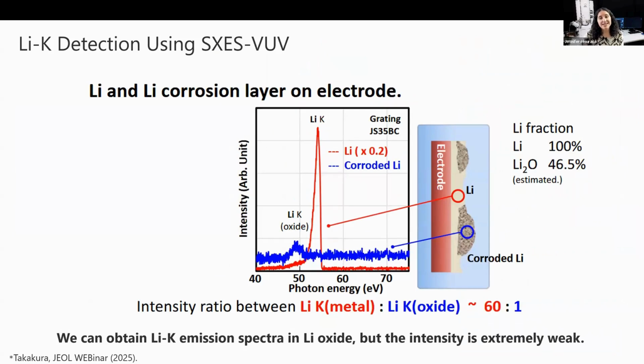However, even though the intensity is very weak, it is still possible to detect lithium in certain oxide compounds with the newest version of SXES. Here we can see the spectra for lithium and a lithium corrosion layer on an electrode. The ratio of intensities here is 60:1, which means the detection will require much longer measurement times for oxide compounds than for lithium in any sort of metallic form.